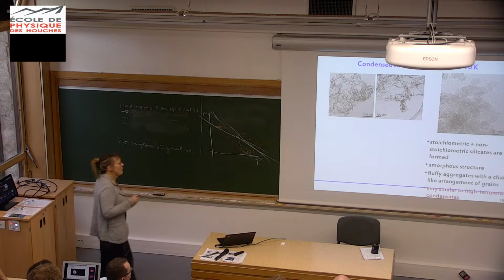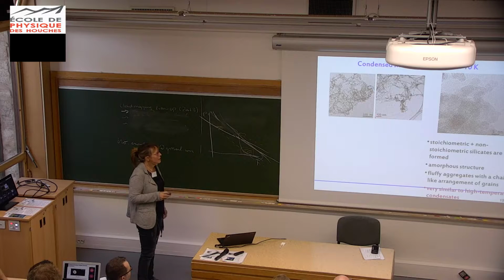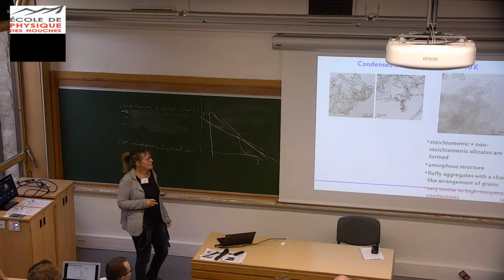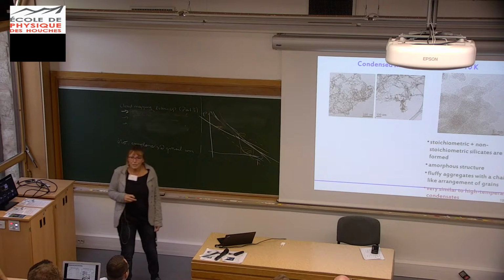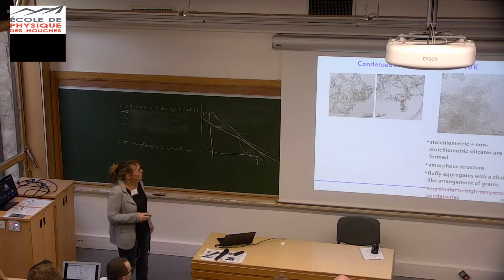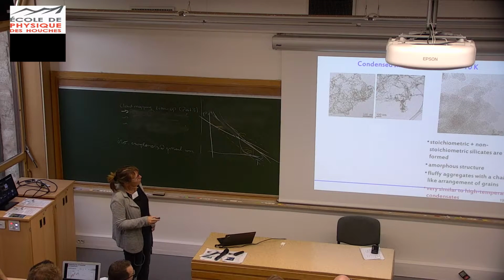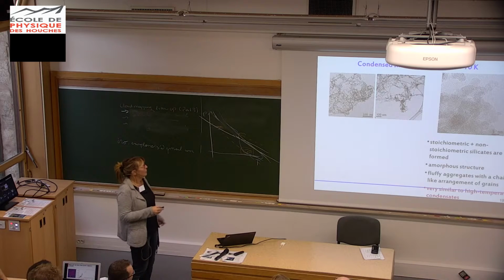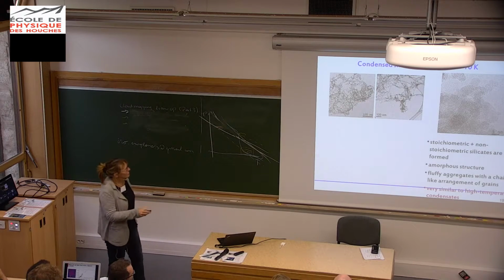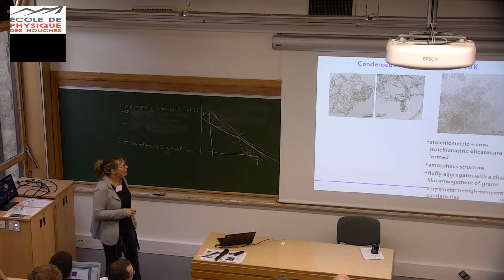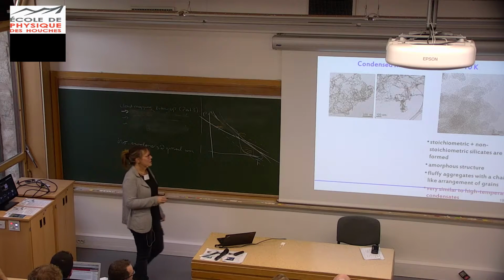What I want to show finally is that the structure of the material is very similar to the high temperature material. It's amorphous, made of small grains, already agglomerated, and this is a low magnification image of these clusters. You see they are very fluffy, with chain-like structures.